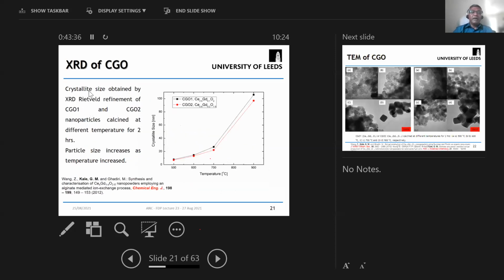So what we found, interestingly, was that there is no linear relationship between the temperature and the particle size. We found an exponential type of relationship. So initially, the growth of the particles is much slower, and then suddenly at 700, it takes off exponentially. Up to 700, the growth rate of the particles is much smaller compared to that at 900 degrees Celsius.